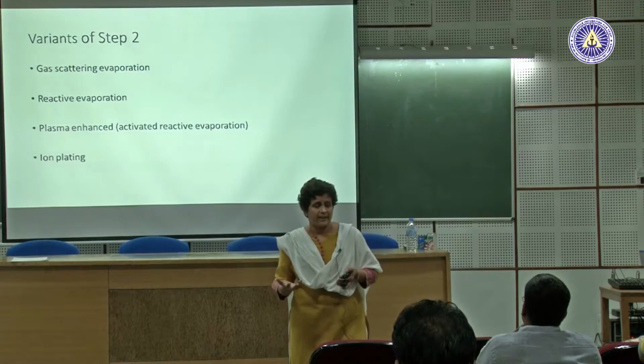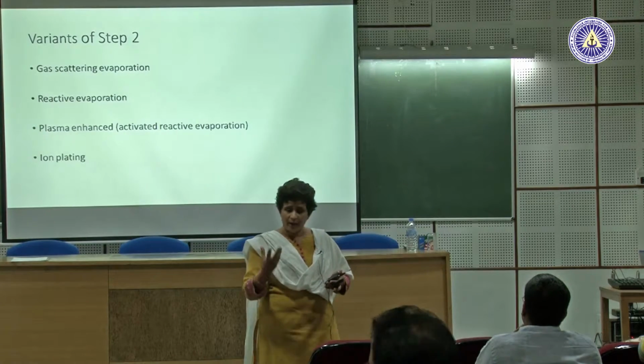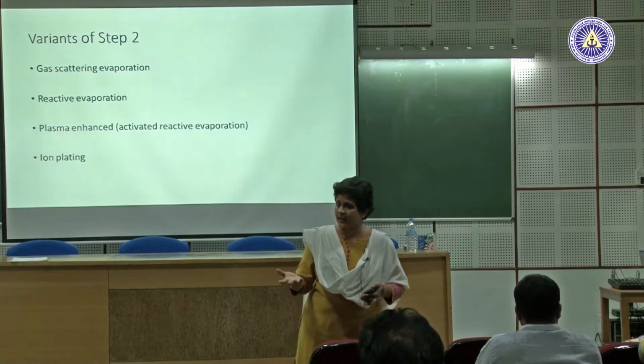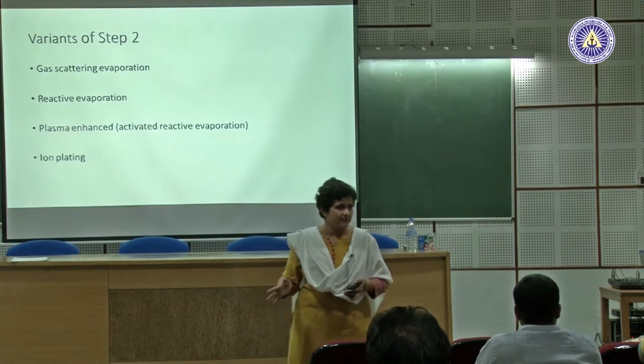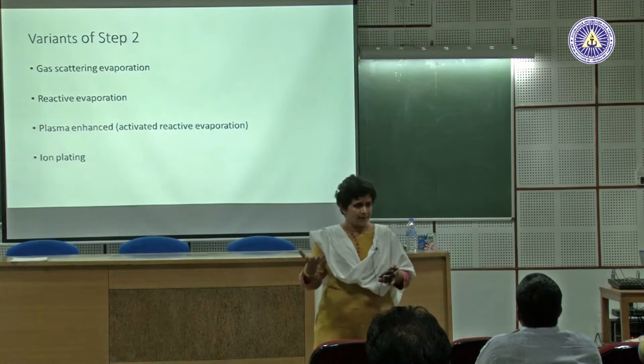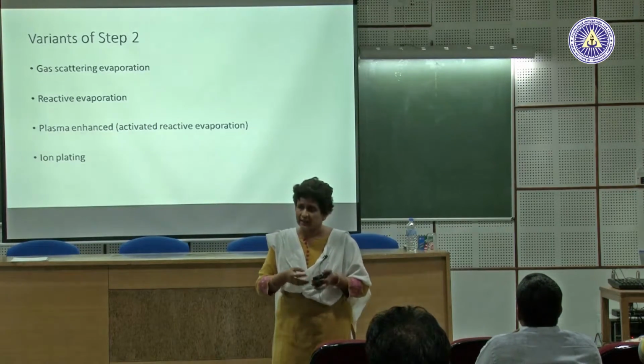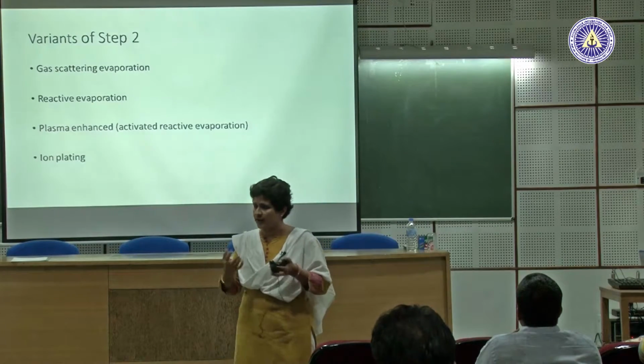Let us say I want to make silicon nitride, right. I evaporate silicon, I put it in nitrogen gas, it will not form silicon nitride, right. We know that we need to have a higher temperature in order for silicon and nitrogen to react. The activation energy required is more.